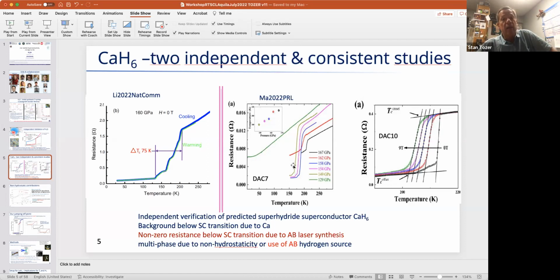And Ma's group loaded many cells. Some showed zero resistance. I'm showing the ones that don't, just because they go to the point that when using AB as the hydrogen source and pressure medium, often you end up with non-zero resistance, as Ma finds here. But it's clearly a superconducting transition, because if you apply magnetic field, you get the suppression. Not as much as people would like to see. They don't see the broadening that they want to, but again, we're up at fairly high temperature, and so one shouldn't expect to see that much broadening.